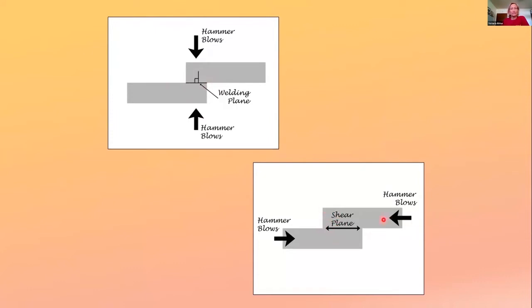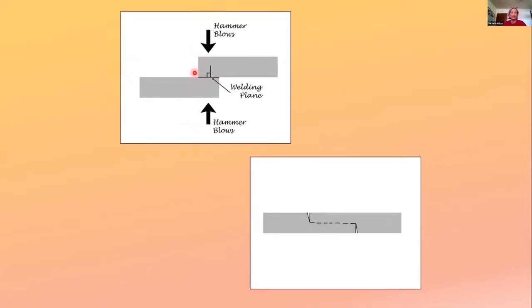Having metal positioned here, hitting from here or straight on top, you've entered the shearing plane, and that will not weld. That'll just kind of bust your pieces apart. So as you're hitting here, the metal is going to be pushed down into this bottom piece. And since we have our nice welding plane, this straight edge becomes a problem. In fact, it'll act like a chisel and push down in here to create a crack. This will all weld, but you'll have these cracks here because this is in a shearing plane. It's not perpendicular to your hammer blows, so the shearing plane shears your metal. So get ahead of it, outsmart it.